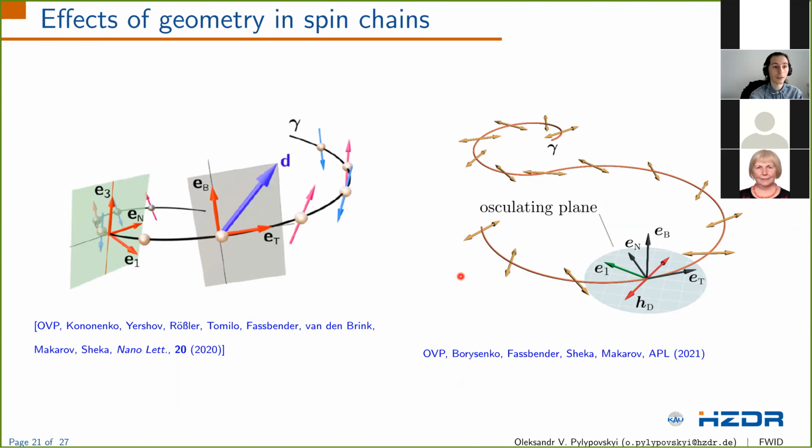To summarize, the geometry-induced changes in magnetic responses can be divided into two groups. The exchange interaction comes into the game via the spatial derivatives. It leads to the chiral response linear in the curvature and torsion. The exchange-driven anisotropy brings about the easy axis, which determines the direction of spins in the absence of the intrinsic easy axis anisotropy. The multi-sublattice intrinsic structure of antiferromagnets enables geometry-driven effects which stem from anisotropy itself. This includes the tilt of the in-plane easy axis, which is pronounced in the spin-flop phase, and the homogeneous DMI of the longitudinal symmetry.